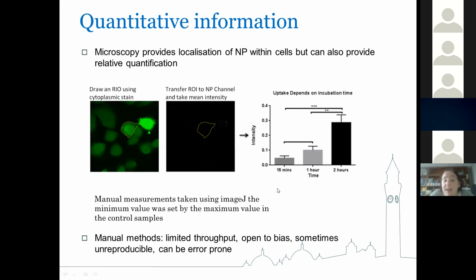What we find is what we expected, in a sense, that the amount of uptake of the nanoparticles will depend on the incubation time. So longer times will allow more particles to enter. And this is very much related to the fact that it's receptor-mediated uptake. So each of the receptors will have a certain length of time that it requires to turn over. So once a particle makes contact with the receptor, it then undergoes the process of internalizing it and then is re-available for the next particle to bind. So we definitely find that the number of receptors on the cell surface is the limiting factor, and their turnover time.